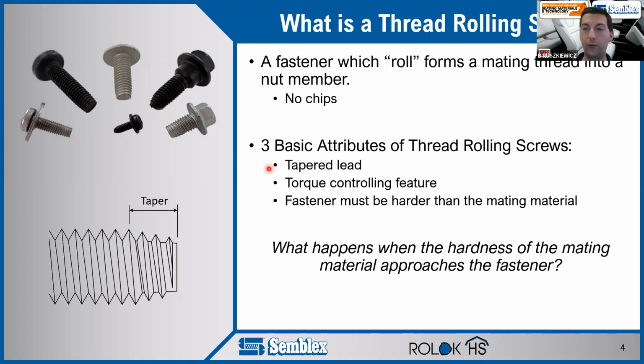One is that they have a tapered lead, and this is what separates them from traditional machine screws. So if we look at this picture on the bottom left, you can see where all of these thread crests are the same height, and then they start to taper down. This is the tapered lead area. This allows these screws to slowly form threads into the part, enabling a nice clean thread formation.